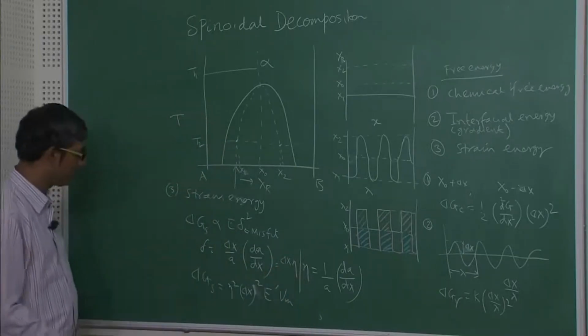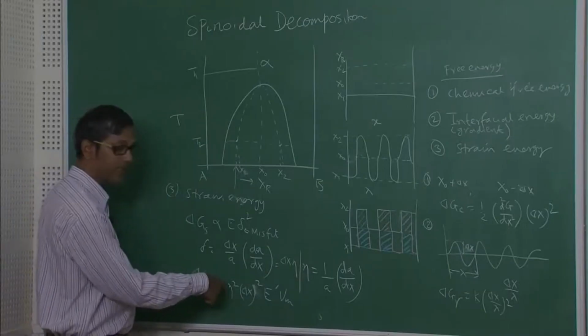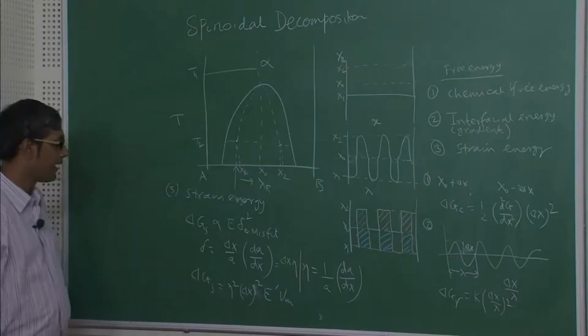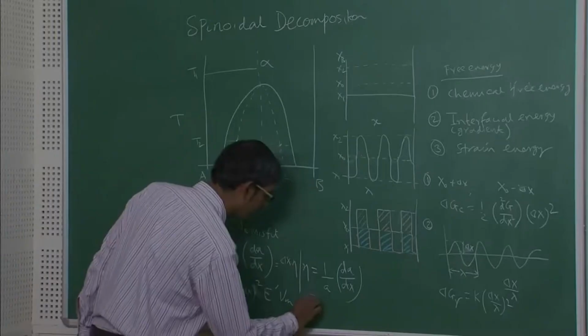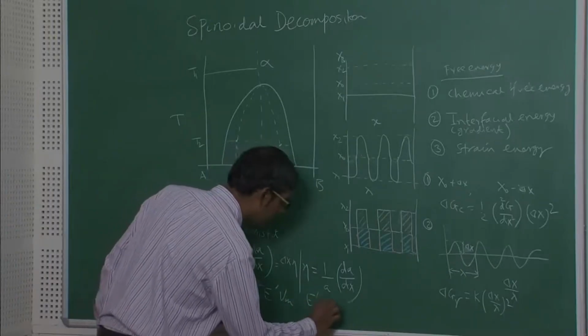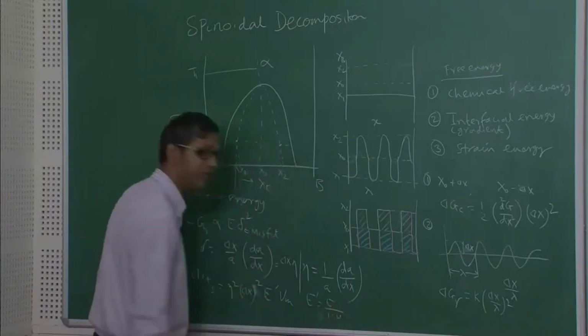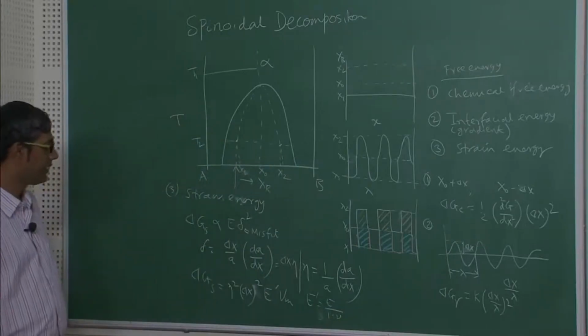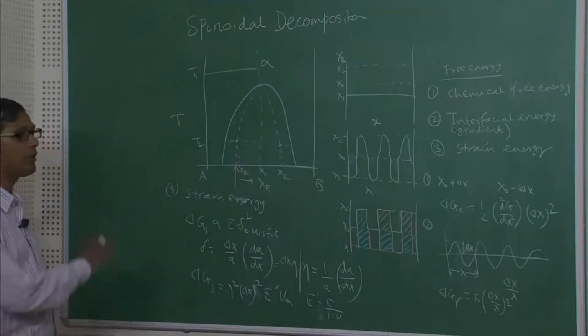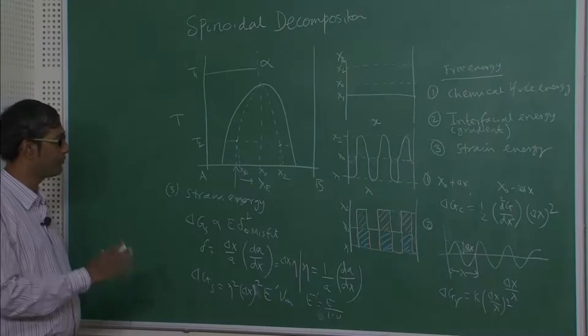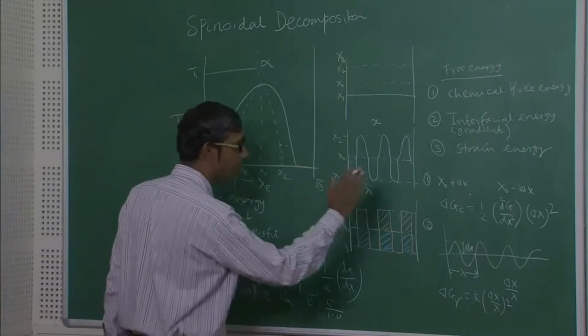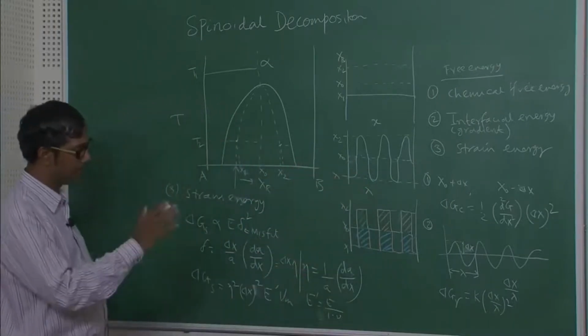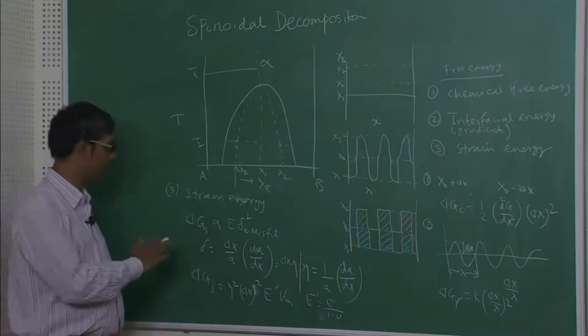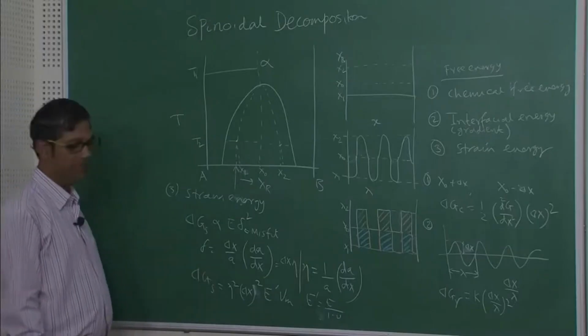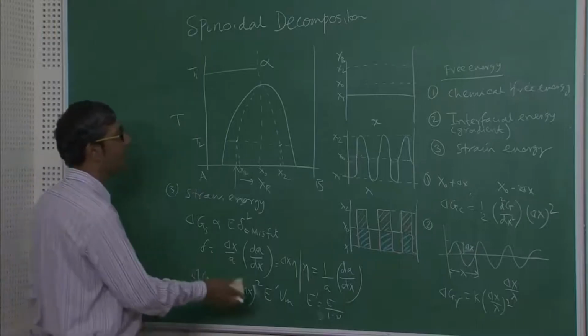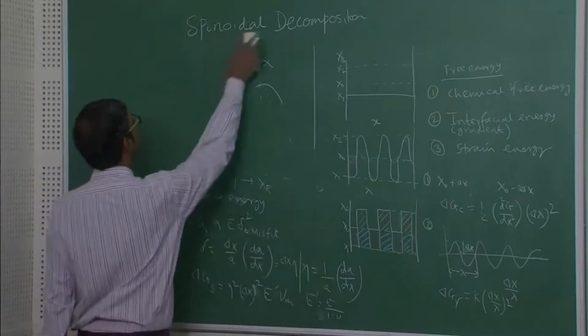That is why if I have to calculate delta square, this becomes eta square and delta x square, and E prime is basically E divided by 1 minus nu, where nu is the Poisson ratio and Vm is the molar volume. So now we have all the things together. We have the expression for chemical free energy, the expression for gradient energy and the expression for the strain energy. So let us now put them together, okay. I will erase some part of this so that I can explain it to you.